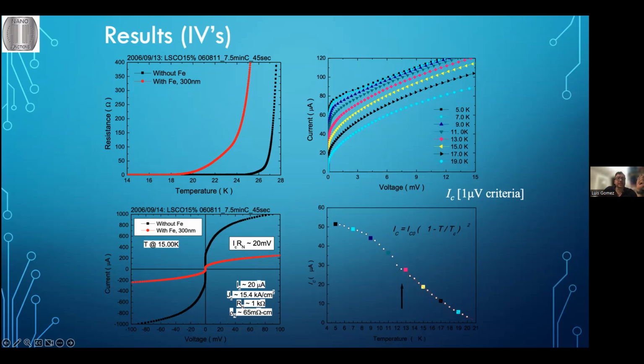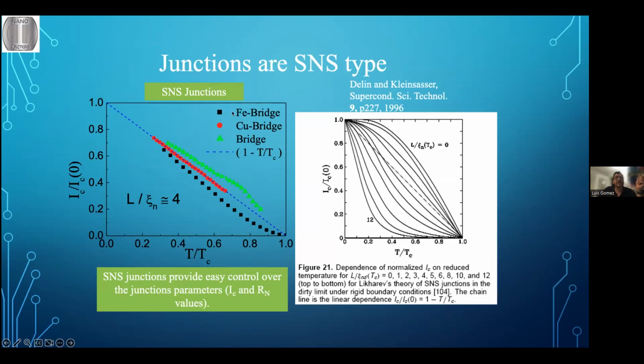Okay, we went further and we created a bridge with iron, which is the red curve. We also normalize the values with the critical temperature, because there are 3 different systems, so they have different critical temperatures. The black curve represents the bridge that has the iron. The other one has copper, which is non-magnetic, but it has a different curve. The last one, the green one, is just the plain bridge with nothing in it. And this is a curve that represents 1 minus T over TC.